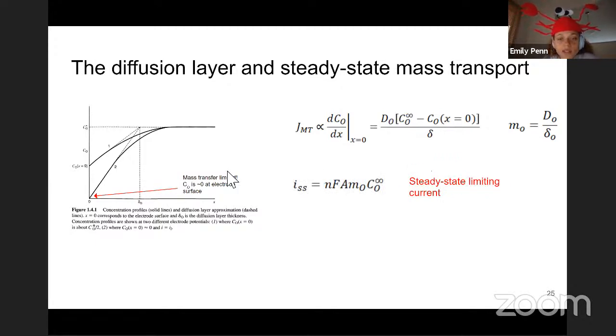If we input that this concentration is equal to 0 at the electrode surface, and then we plug in MO for this diffusion divided by the Nernst boundary layer, and then we know that the flux is equal to the current divided by N times F times the area of the electrode, we can get a steady state mass transport limiting current, which is a function of the bulk concentration and the mass transport coefficient.